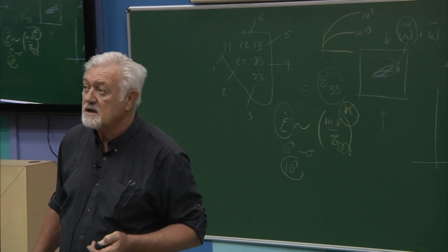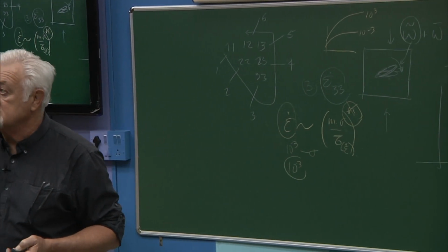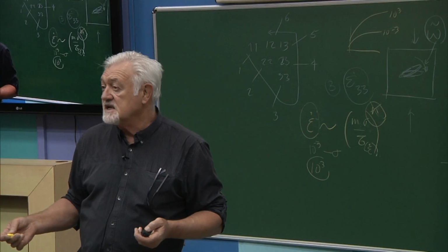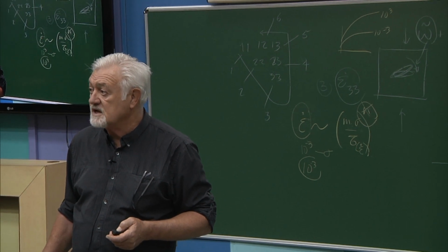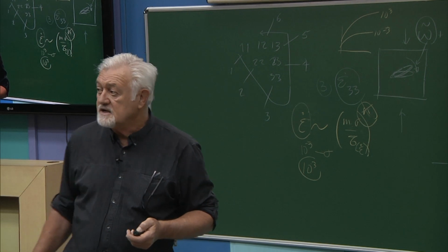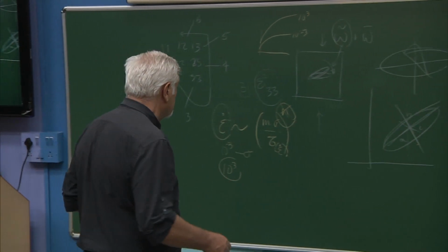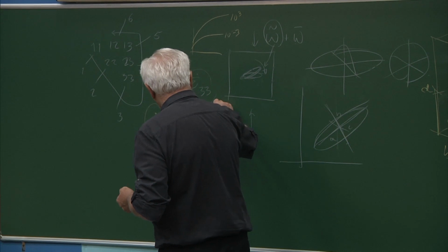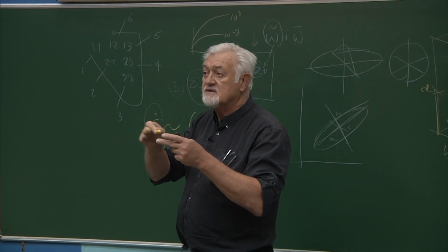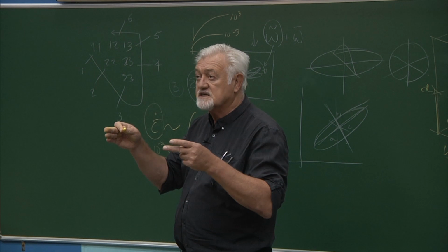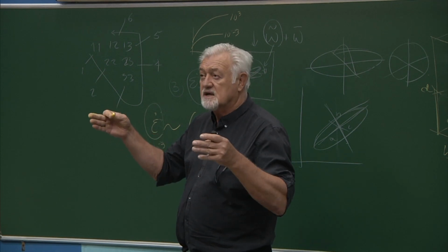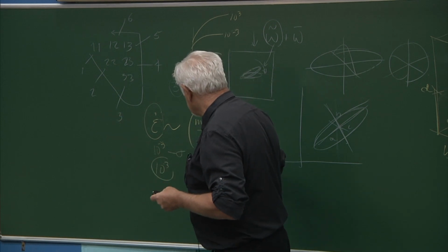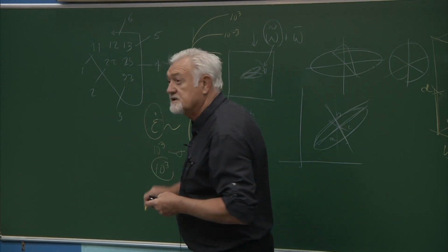Yes? The critical stress. Yes, the critical stress, in general, is going to be a function of how fast you want to deform your material. So it's a function of that. Sometimes you can mimic that with this parameter n, but only in limited ranges of rates. If you really want to do that for an extended range of rates, it is better to put that dependence here.